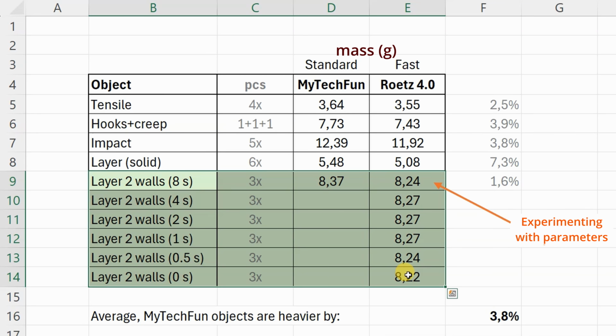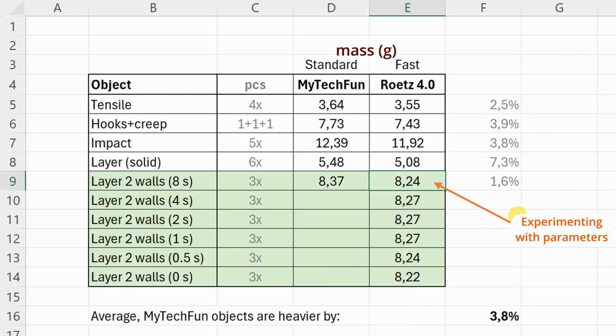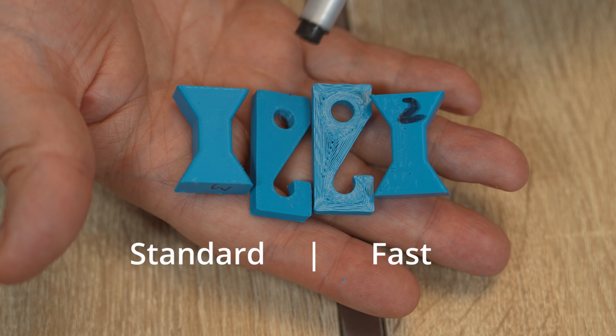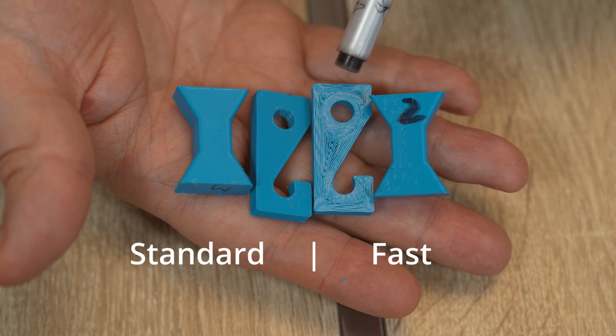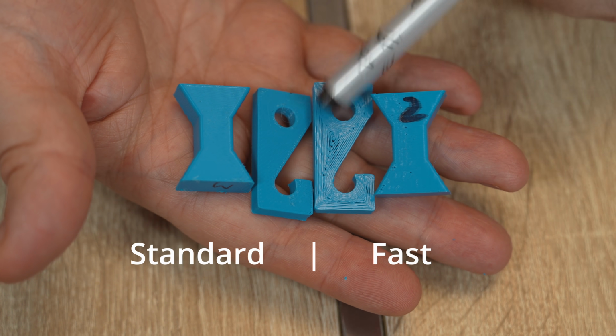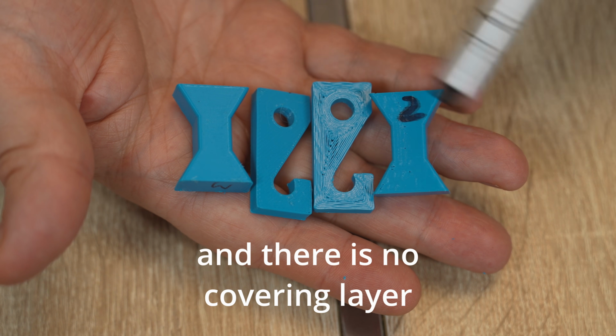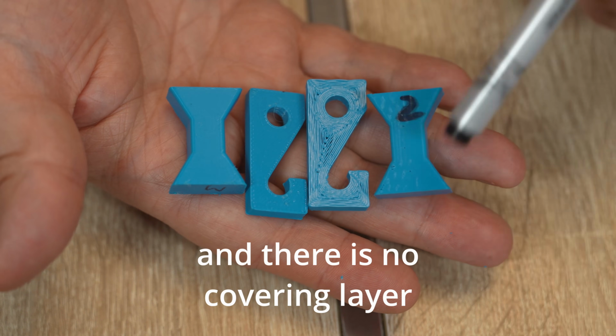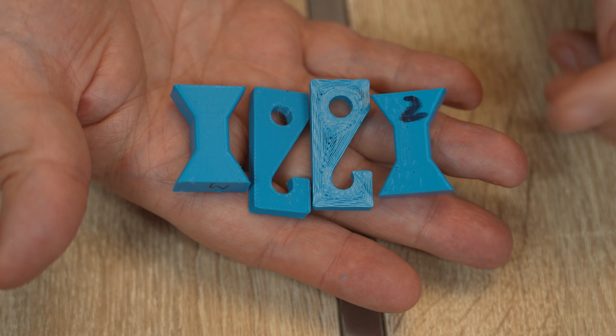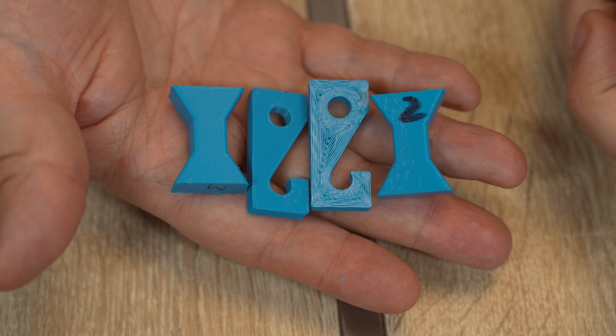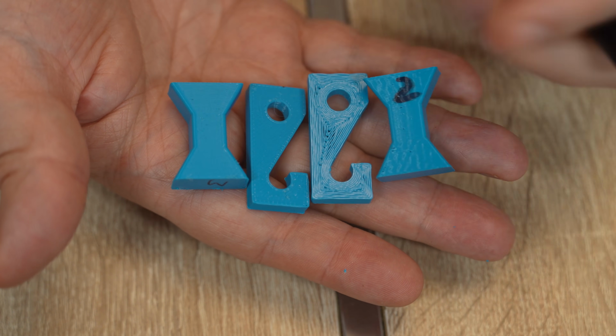These are the objects for the layer adhesion, 2 walls and 20% infill, and this one was experimented with parameters, but the rest we can see more or less constant values. Only here we can see some signs of under extrusion. We will see how it affects the layer adhesion. Even without numbers, I can see some signs of micro under extrusion. For example, here I can see some micro gaps between the walls. But overall this is quite good. I mean, I can see some waves here compared to this one, but this test is not about the looks, but about the strength. So let's test them.